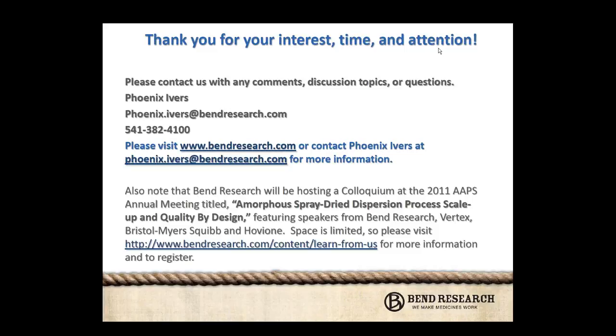Yeah, sure. One of the biggest ways to impact spray dry capacity is by how much solids content you can get into the feed, and that can be limited either by API solubility in the solvent or just the viscosity of the resulting spray solution. So if there's too much polymer in the spray solution, it can actually get too viscous to atomize. So that's kind of a big parameter. And in terms of how it affects the spray drying particle attributes, I would say with this methodology you can tune such that you can achieve similar spray dried particle attributes at both the higher capacity and the lower capacity.